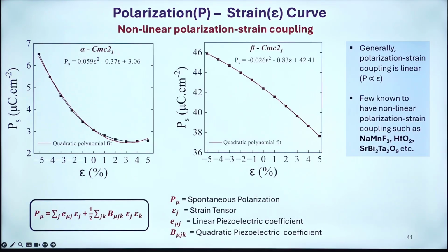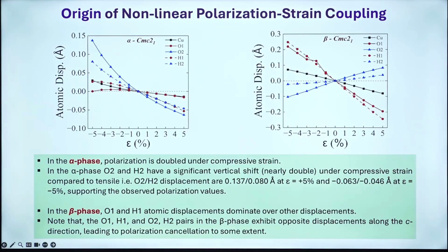So for this alpha phase, Cmc21, we have a quadratic polynomial fit, and the polarization behaves in this way. For the other phase, it starts from 46 and decreases, while this phase is already 42 or something. So they both have a different kind of behavior, but both have this quadratic polynomial fit. The spontaneous polarization is coupled with the strain tensor, and since it is strain dependent, we also have a linear piezoelectric coefficient and a quadratic piezoelectric coefficient. So then we tried to look into that also, and what is the origin of this non-linear polarization with respect to the strain. Here we try to see for each atom specifically.